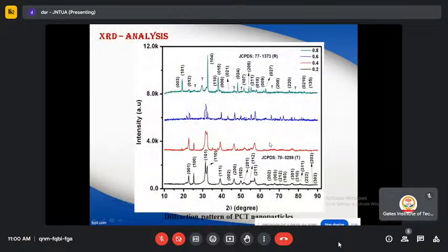So, coming to X-ray diffraction. Initially, in order to study the size of the particles, the synthesized powder has been analyzed using an X-ray diffractometer. X-ray diffraction analysis was carried out to characterize the crystalline nature and structure of the prepared sample. The XRD spectrum was recorded with the help of a Bruker D8 X-ray diffractometer having a radiation wavelength of 1.542 angstroms. The X-ray was scanned over the titanate samples in the range of 2 theta between 10 and 90 degrees with a scan rate of 0.02 degrees. The obtained diffraction pattern was used to detect the crystalline phases in the specimen and to analyze the sample's structural properties.